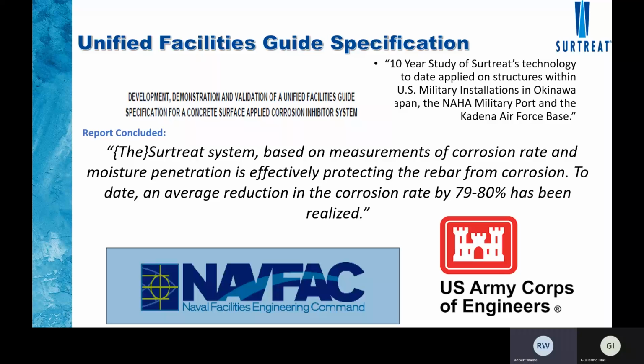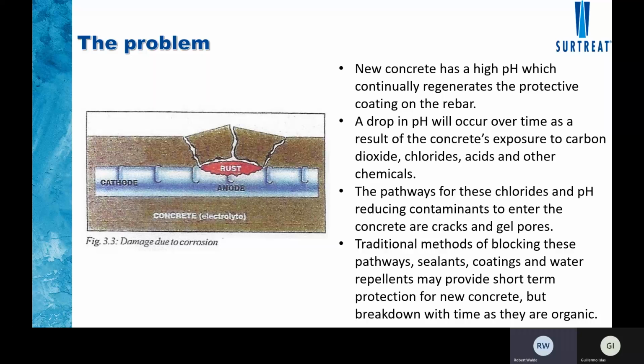And we also determined that the strength of the concrete had been increased by about 1,000 psi, and the rate of water penetration had been taken to 0. And these properties continued to prevail and continue to today. And we've now been asked to come back and treat more concrete at the Kadena Air Force Base, which will be done soon as the coronavirus allows people to get back to work there.